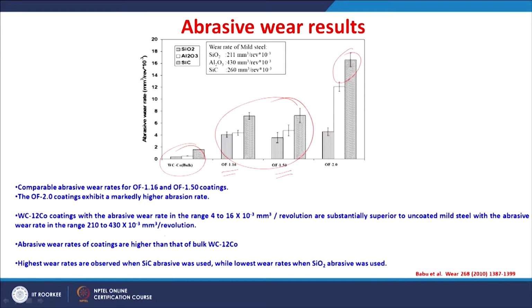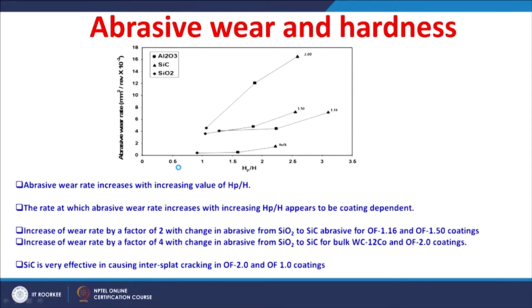per revolution. So, the abrasion wear rate was higher for the coatings than that of the bulk material, as expected, but higher wear rates are observed always when silicon carbide was used, whereas the lowest wear rate was observed when silicon oxide was used, and the abrasion wear rates were intermediate when the aluminum oxide abrasive was used. So, it gave an indication that the abrasive wear is highly dependent on the abrasive particles you are using.